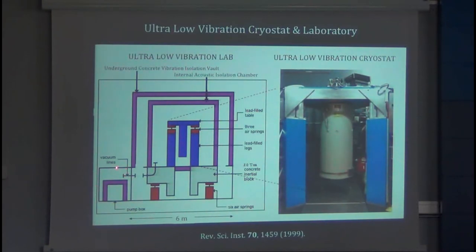So here we have micron vibrations. Here we have a few tens of nanometers. The floor of our room is a few angstroms. The table is moving only a few picometers at room temperature. And then by the time we cool down below 1 Kelvin, the STM tip is moving only a few femtometers. And that's so stable and so quiet that we usually keep the same experimental field of view oftentimes for years, because at those temperatures and at this vibration level, there's no way that you can lose it unless a graduate student makes a mistake.